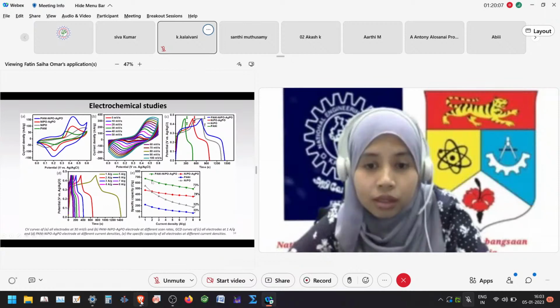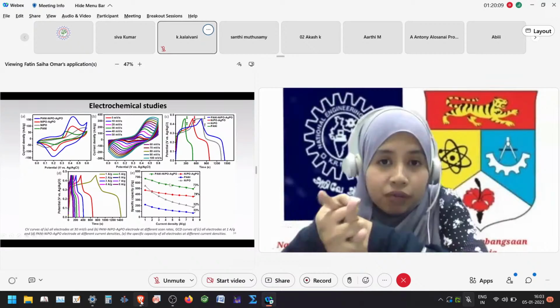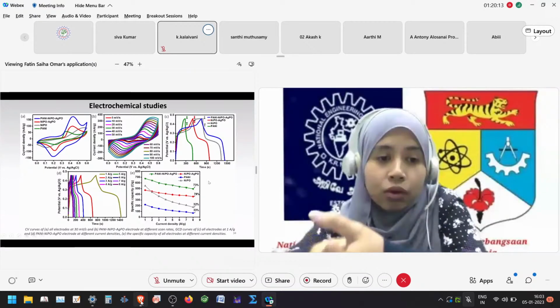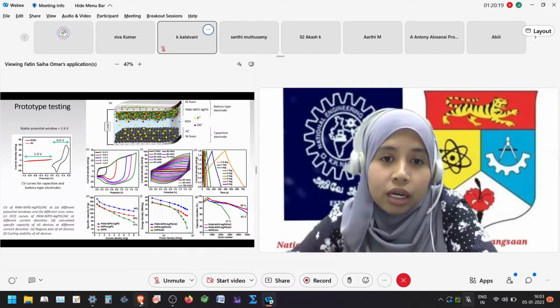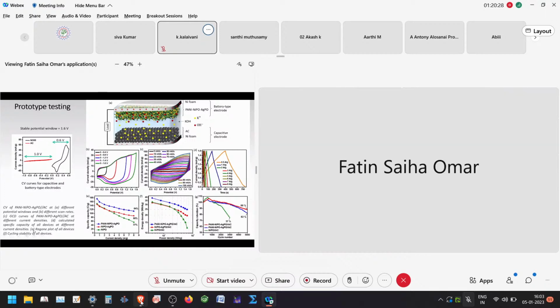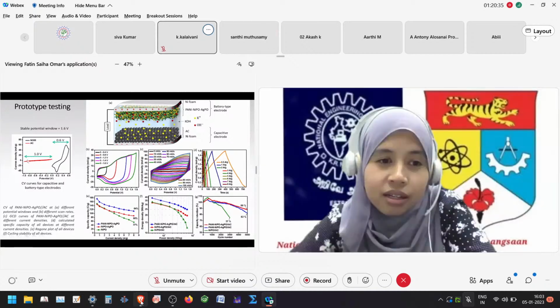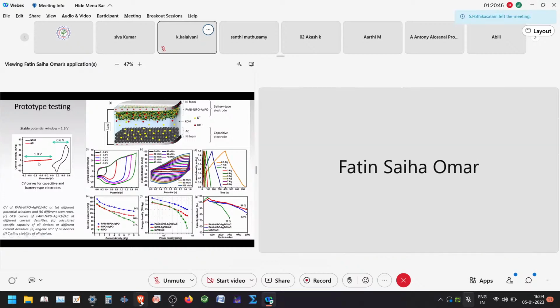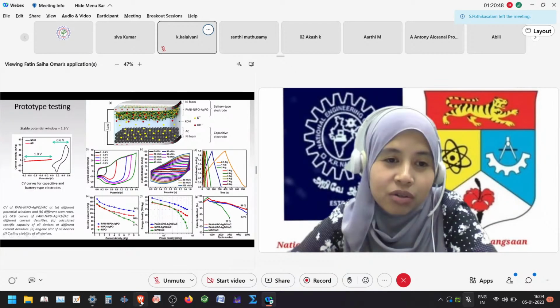Okay, after we tested the performance of a single electrode, we fabricate the device. So before we fabricate, we can check the CV profile of the capacitive electrode and the battery-type electrode. In this, we use activated carbon as the capacitive electrode, and the battery-type electrode is nickel phosphate. Okay, so if you look, the capacitive electrode has a potential window of 1 volt, and the battery-type electrode has a potential window of 0.6 volt.